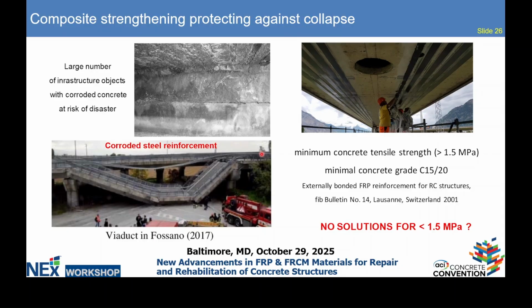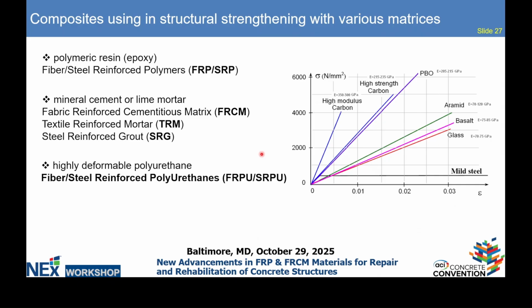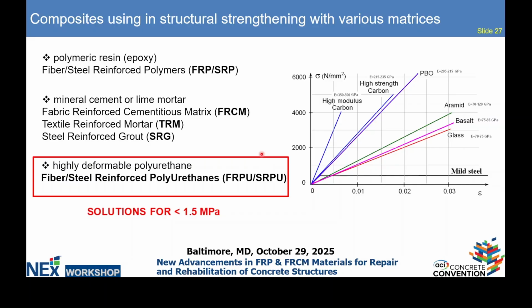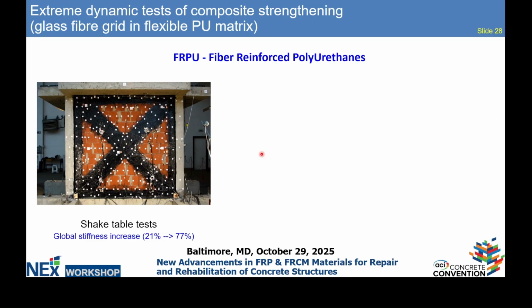guideline is that we can use it when the bonding strength, I mean the pull-off, is at least 1.5 megapascal. Is there a solution for lower values? I will talk about this. So nowadays we are using polyurethane, polymeric resin as epoxy, FRPU, also FRCM system as Christian presented, and also the new generation PolyUrethane Flexible Joints. It is used for fiber steel reinforced polyurethane system. And this is able to bond to the substrates with lower strength.